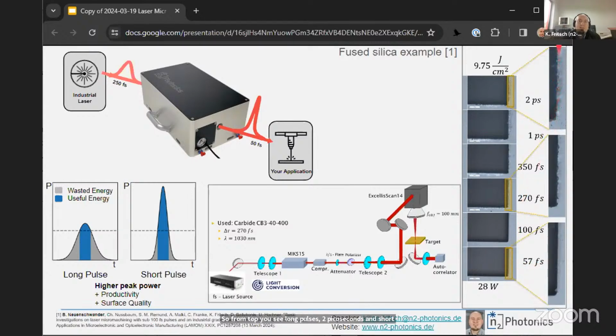And for the long pulses, we have kind of frayed edges, not very clean edges. And the shorter you go, the better the edges become. So 270 femtoseconds, this would be the current industry standard, so to say, for femtosecond lasers. You still see the frayed edges. However, if you go down to sub 60 femtoseconds, you suddenly start to see very, very clean edges of these squares. So for us, what this proves is that there is some advantage to using shorter laser pulses for micromachining that we could provide for basically any industrial grade femtosecond laser system.